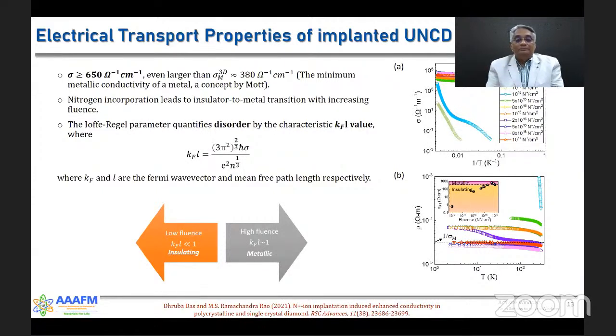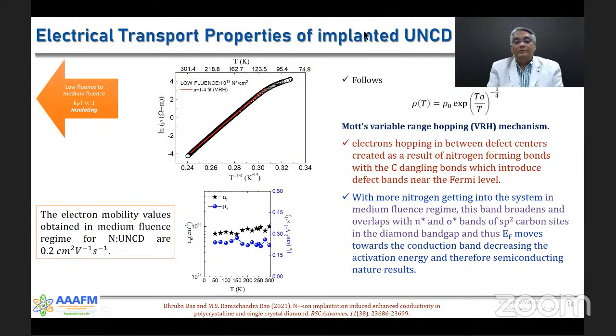in the diamond film. We have been able to see an enhanced conductivity with nitrogen and phosphorus doping. The low fluence gives rise to an insulating behavior, high fluence gives rise to a metallic behavior, and such high conductivities have not been seen so far in the implanted diamond films, either with nitrogen or phosphorus. So we have fitted the resistivity data with the standard Mott variable range hopping mechanism. The electron mobility values obtained in the medium fluence regime are about 0.2 centimeter square per volt per second.